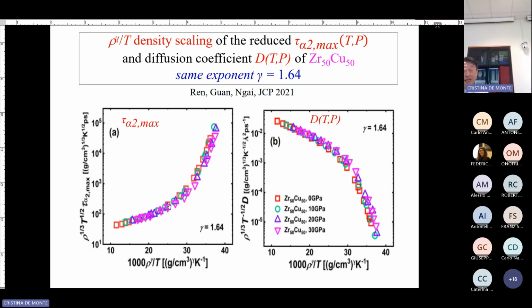So this is again another case of metallic glasses. Same thing. We did the simulation and we found the same thing for the dynamic variable which is related to the JG relaxation. This is called tau alpha 2, the non-Gaussian parameter, but it's related to the JG relaxation. This is diffusion. So both of them are doing the same.